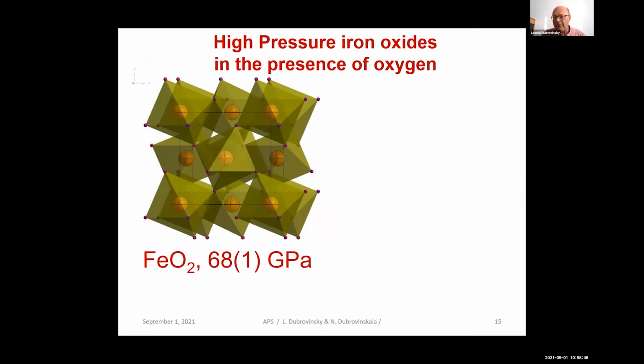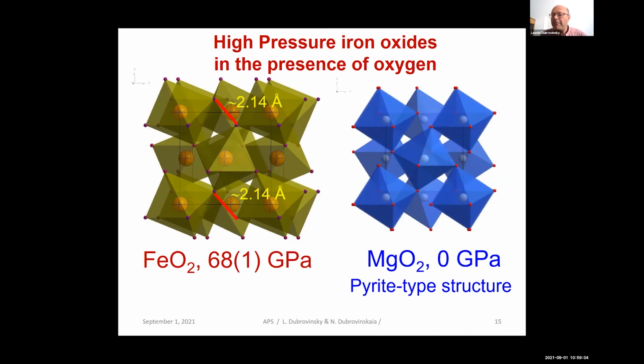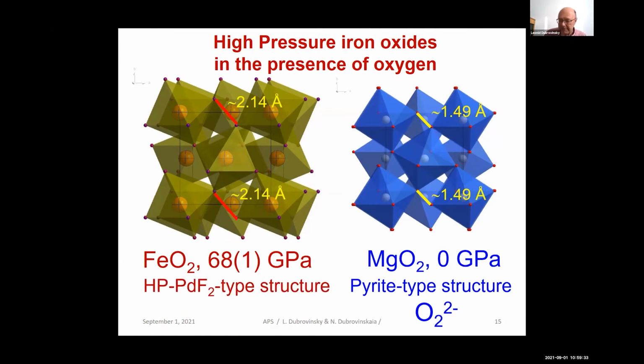Yes, we observe it for both FeO2H and FeO2. This is an example of such a phase at 68 GPa. If you look carefully at the oxygen distance, we will find that they are on the order of 2.14 angstrom. If you compare now with real pyrite type structures MgO2, we see that in the O2 the OO distance is on the order of 1.5 angstrom. Of course, we cannot expect that the compression of O2 bonds will lead to the elongation. So, in fact, we are dealing not with a pyrite type, which was assigned qualitatively, but we are rather dealing with a high pressure palladium fluoride type structure, which we can determine from a single crystal diffraction.